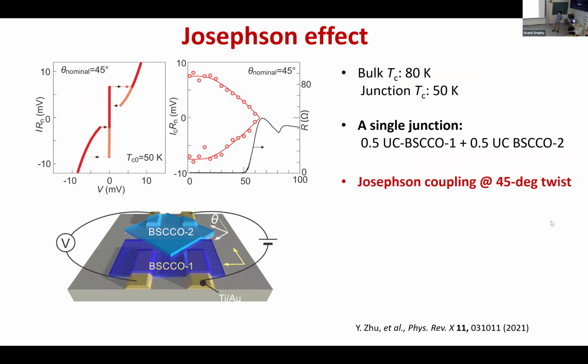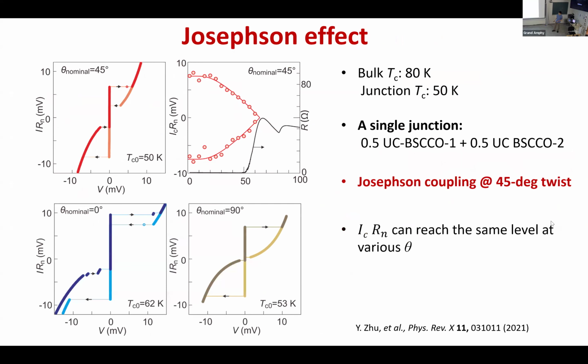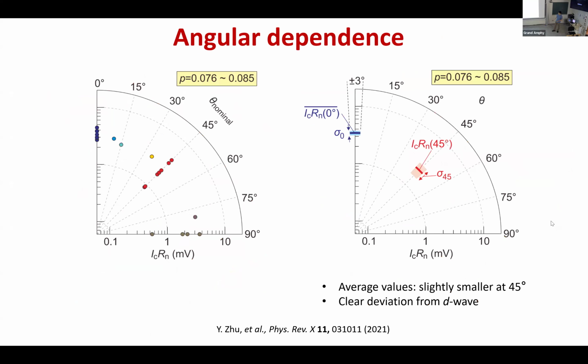And we see even at 45 degrees, we see the Josephson tunneling. It's comparable to either 0 degrees or 90 degrees, and we also measured a lot of samples, and in the end, statistically, we see this. I mean, this is in the underdoped regime, but we see that it's kind of comparable. So either 0 degrees or 45 degrees, we see the Josephson tunneling.